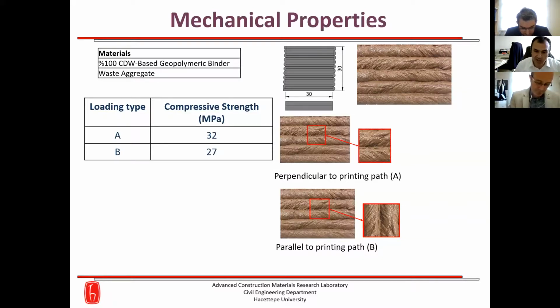And in terms of the mechanical properties of our CDW-based mixtures, it can first be stated that the print strategy strongly influenced the mechanical properties of the printed structure. Our nozzle was rectangular geometry, and we cut the printed sample to be a cubic sample with a dimension of 3 centimeters. We loaded the specimens in different scenarios according to the printing direction, and different results were obtained. For example, if we load the samples perpendicular to the printing path, it resulted in 32 megapascal. If it is parallel to the printing path, the compressive strength is 27 megapascal. It's very close, but we are still working on these performances to be equal. If the bonding is perfect between the two layers, these two compressive strength values are going to be close to each other.